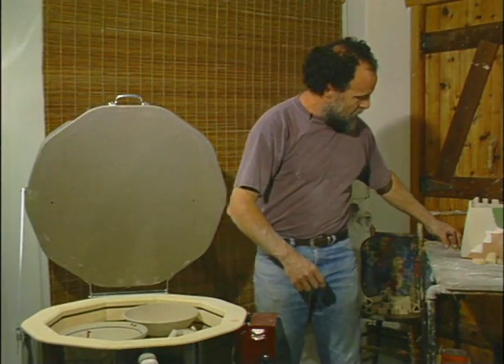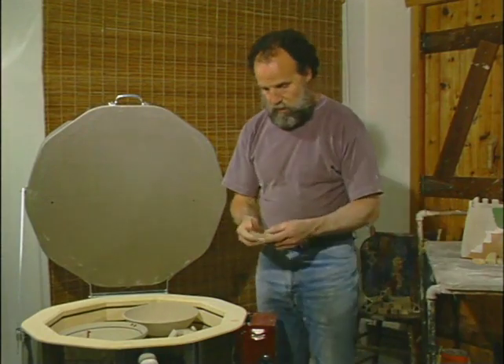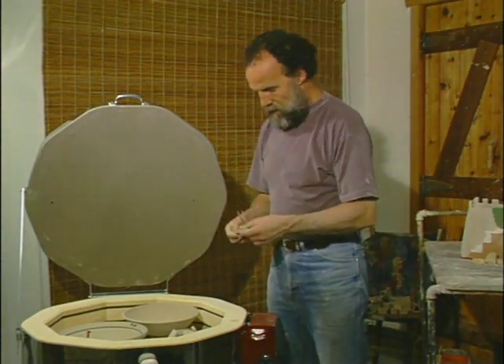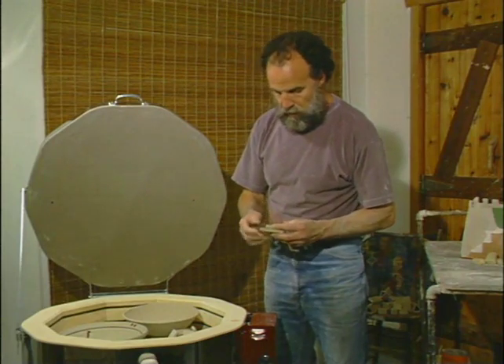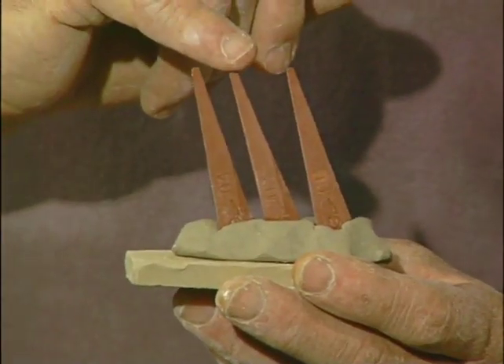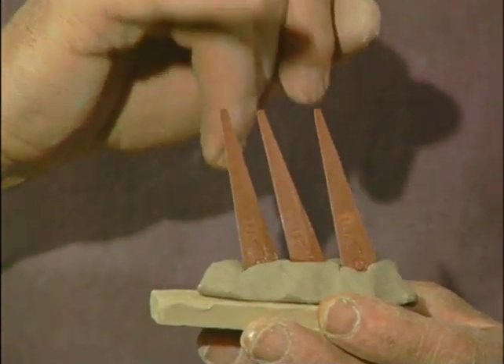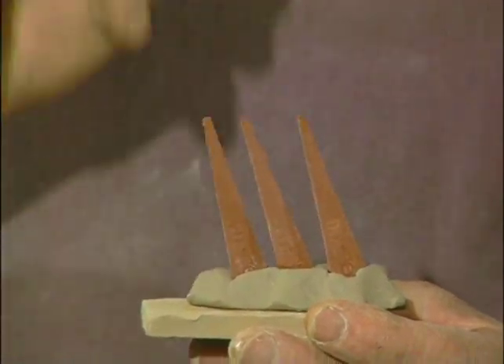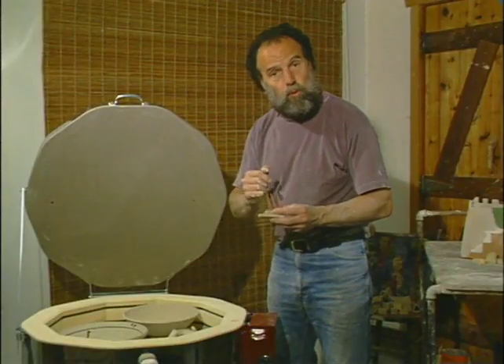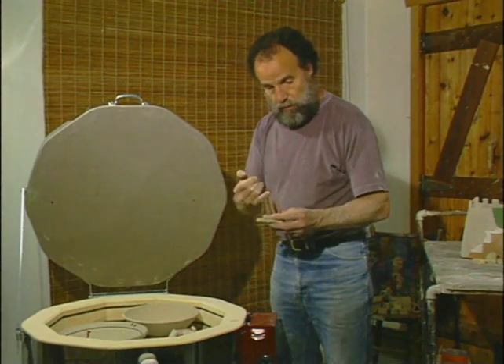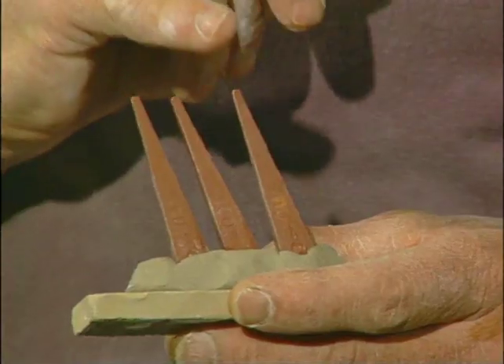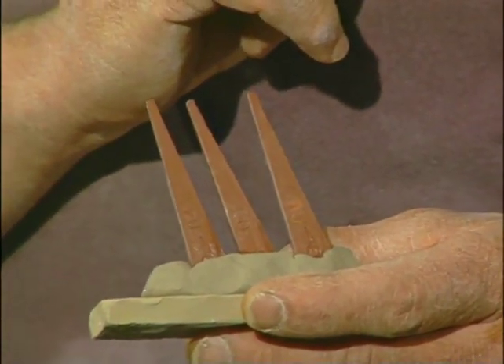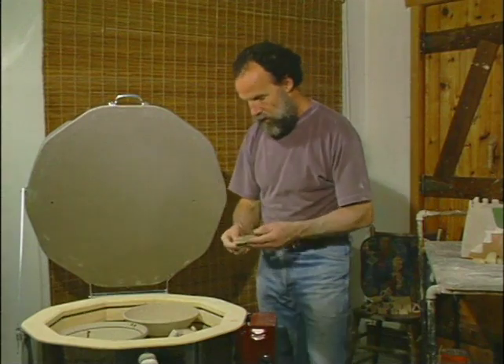And lastly, the cones. The difference between the bisque firing and this one is that we've got 3 cones now. We're shooting for cone 02, indicated by the middle one, so we've got a lower cone here, cone 04, to more or less indicate to us that it's about time, so that we can watch this one. And this is a cone 01 here as a guard cone against overfiring.